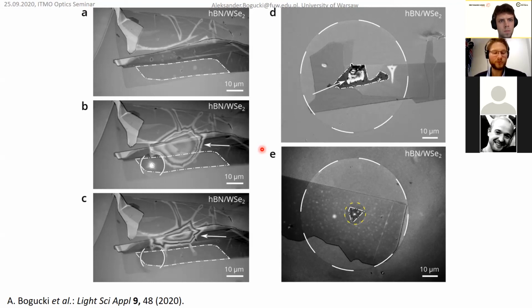But for example, we were also trying to play with these printed structures by trying to move them. When they are already printed on a glass or on a substrate, we were poking them from the side just to see what would happen. It turned out that we can move them on the sample. If you poke hard, they will just move or fall down. So we can detach them from the substrate as well. However, when we would like to detach them deliberately, for example to clean the sample, when you print on a glass and now would like to remove all of the printed nanostructures, we can't do that. We even tried quite hard acids, and probably the hardest acids will work, but regular, quite mild stuff that will not destroy the samples will not remove the object.